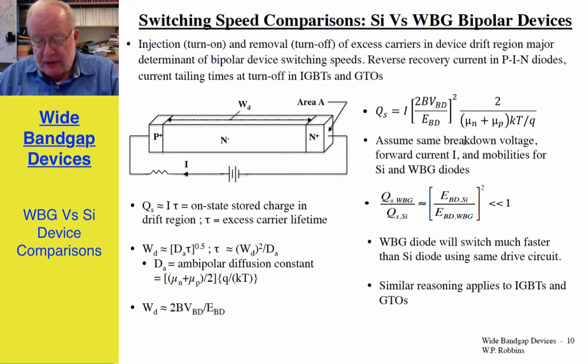If we compare a silicon diode with a wide bandgap device, one can show that for the same current and the same breakdown voltage, and assuming the mobilities are the same, the ratio of the stored charge in the wide bandgap material divided by the stored charge in the silicon device is proportional to the square of the breakdown field strength of silicon divided by the breakdown field strength of the wide bandgap device. And this is going to be much less than 1. And so the wide bandgap diode will switch much faster than a silicon diode using the same drive circuit. And similar reasoning would apply to IGBTs and other bipolar devices such as GTOs and thyristors.